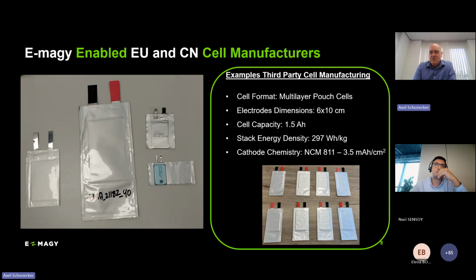We have a battery lab, so we can make coin cells and pouch cells to a certain limit. But what we have done is we went out and enabled cell manufacturers both in Europe and in China so that they know how to work with our material, that they can make slurries, that they can make 100 meters of coatings, and they can make series of cells. And that is what we use to supply cells via these manufacturers to drone or consumer electronic projects at the moment. So in the left picture, you see a selection of pouch cells for different applications with different dimensions. And the right one shows a project where we let make 1.5 ampere hour cells, around 300 watt hours per kilogram, by a European cell manufacturer in this case.